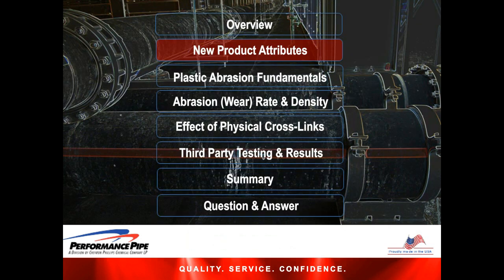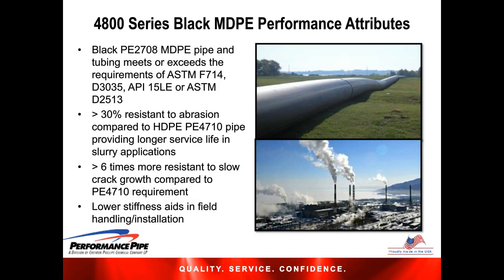For the next couple of slides, I will review some of the many benefits of our new medium-density 4800 series pipe systems. The key performance attributes of the new 4800 series pipe are that we now have black PE 2708 MDPE pipe and tubing listed in PPI's TR-4 that meets or exceeds the requirements of ASTM F714, D3035, API 15LE, or ASTM D2513. As you will see from Ashish's slides that are coming up, the pipe has greater than 30% better resistance to abrasion compared to HDPE PE 4710 pipe, providing longer service life in slurry applications.